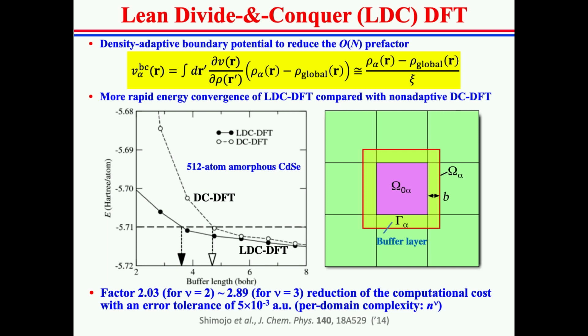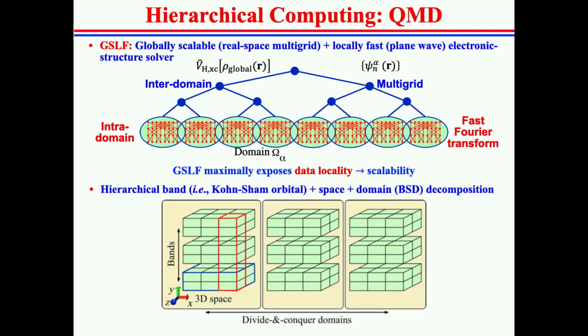This is the convergence of energy as a function of the buffer thickness. The lean divide-and-conquer energy converges much faster, and this translates to a factor of 2 to 3 speedup. We also developed what we call the globally scalable and locally fast electronic structure solver, which uses a real-space multigrid, tree-based algorithm to represent the global density and global Hartree potential, and then uses a plane wave basis within each domain for the local electronic wave function. So this GSLF combines the scalable multigrid algorithm for inter-domain computation and a fast Fourier transform based spectral method in intra-domain calculation. In this way, this solver maximally exposes data locality, thereby achieving scalability.